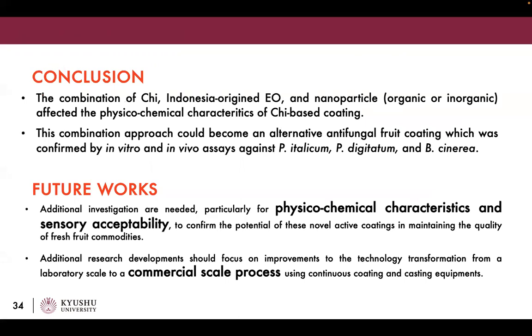And the general conclusion from this presentation is that the combination of chitosan and Indonesia-origin essential oil and nanoparticles, both organic and inorganic, affected the physicochemical characteristics of chitosan-based coating. And this combination approach could become an alternative antifungal fruit coating, which was confirmed by in vitro and in vivo assays against Penicillium italicum, Penicillium digitatum, and Botrytis cinerea.